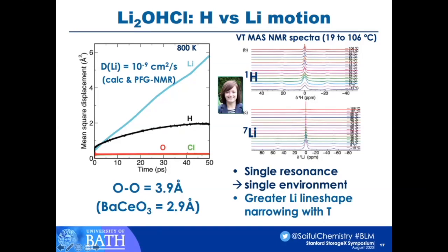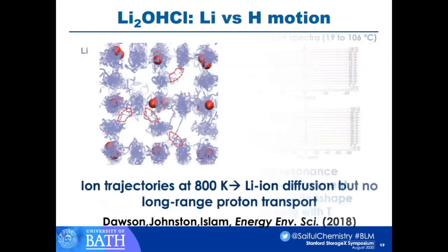So this is variable temperature magic angle spinning NMR from about 19 degrees Celsius up to 106 degrees Celsius. What we find is that the single resonance confirms that the lithium and protons are in a single environment, but also some of the proton NMR suggests that there's no long range transport. It's very much local diffusion or local mobility of the proton from the proton NMR. And this is confirmed from the ab initio MD again.